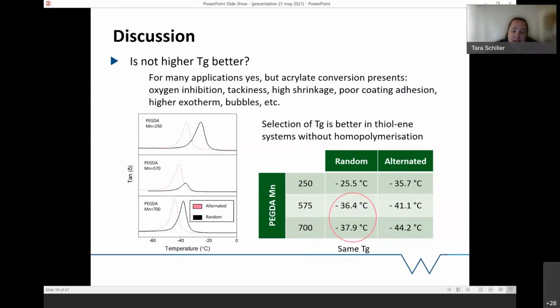The interesting thing here too is that when we increase the molecular weight, which to be fair isn't that much of a difference between the two, we get within reason a similar Tg there. And the difference between the alternated two is much lower between the 575 and 700 compared to the 250 molecular weight. But you can see from the images, we're getting quite a bit of a changeover with the network system in the way they're curing. Which is quite nice.